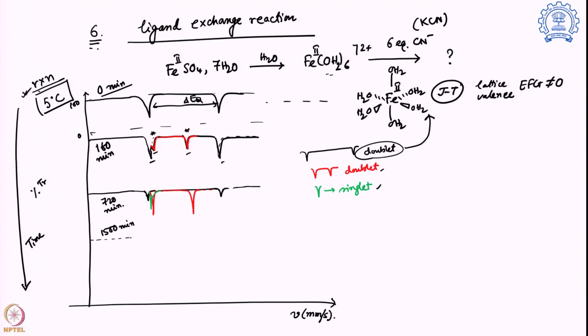More than 12 hours, almost I would say 20 hours now. What we are getting is that this first peak is almost gone. That means the primary iron hexahydrate sample is all exhausted. Not only that, this red color doublet is also almost gone, a little bit higher compared to the original one. And this green color sample is actually becoming the major signature. This is what is happening after more than 20 hours.